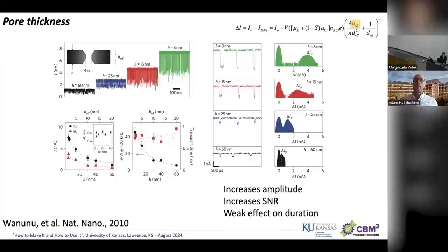Right. Yeah. And so that's because, if you imagine going to a natural extreme, if you take this membrane and you increase it a huge amount, so now it's not nanometers, it's tens or hundreds of nanometers thick, that is basically now a nanochannel, right? And so the same voltage you're applying across this thing now has a lot more to drop across, and so the resistance goes way, way up. So that must mean that as you decrease the thickness of the membrane, the resistance is going down, your current is going up for the same amount of voltage, right?